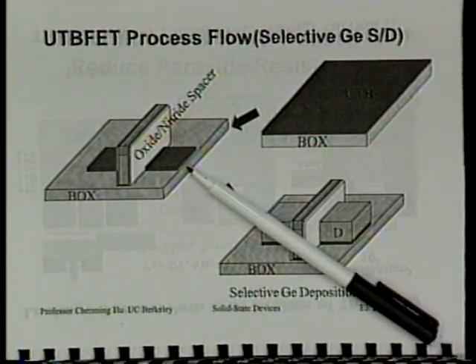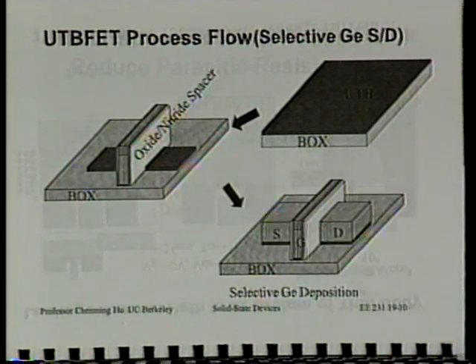Yes? Is this oxidation of an SOI wafer? That's right. But I remember that the oxidation actually happens subsurface at the silicon oxygen interface. Correct. I cannot give you the actual very good answer to that. Apparently, it has to do with the oxidation condition. I'm not familiar with how to do this internal oxidation. If you just grow oxide the usual way, you can still grow oxide on top of the SOI silicon film. So that's why we can make transistors. But apparently, there are certain conditions. If you find them, then it's going to enhance the growth of the oxide at SOI and minimize the oxidation near the surface. And some of this is probably proprietary.